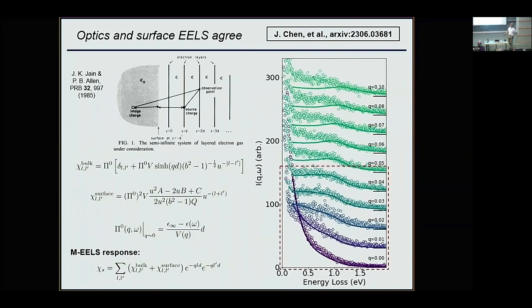So this is Q, the inverse of the wavelength in lattice parameters. This is 100 lattice parameters, that's 50, this is 33, 25, 20. This is energy in eV, so that's 1 eV. My worry is that the energy resolution is not small enough to ever get into the omega much less than v_F Q regime. What's v_F? The energy resolution is 6 meV. It's very similar to what you do with photoemission. We measure the same kinematic range as ARPES or neutron scattering. Whatever your v_F is, say the nodal velocity, that implies a line. We cross that line, so you go to omega much less than that line set by v_F times Q, which was not easy and required a lot of instrument improvements.